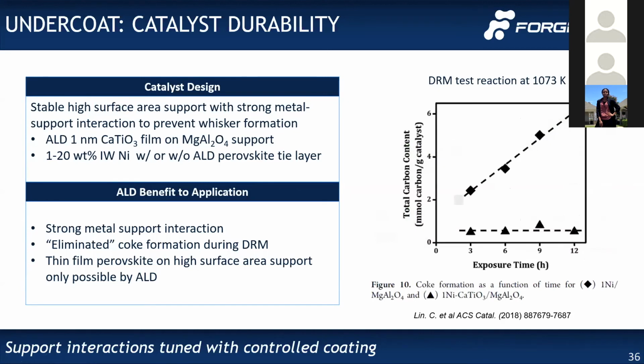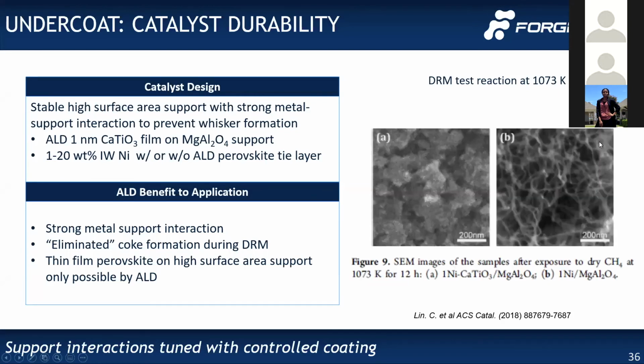With that ALD undercoat, you can actually shut off that coking formation and operate consistently without carbon formation. Without it, you have consistent carbon formation until you plug the reactor. Here are the carbon nanotubes without ALD, and here is with ALD — you do not have that carbon nanotube formation.